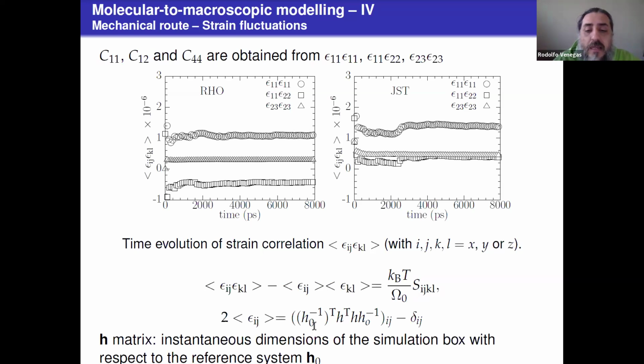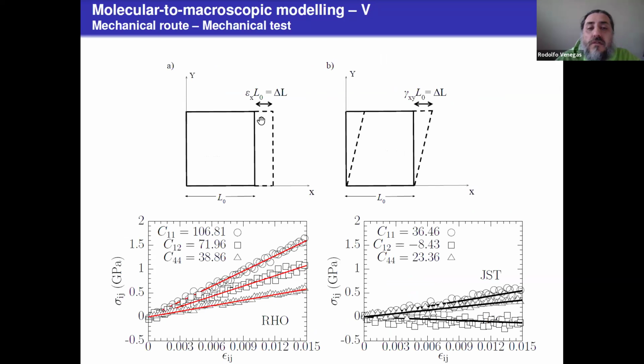In particular, H is the matrix of instantaneous dimensions. When we do the simulation, we work out how this box increases or decreases in size with respect to a reference system, and that allows us to calculate these parameters. So that's the second route. And the third route is, as I mentioned, mimicking the conventional mechanical test. From the stress-strain curves, we can linearly fit in the small strain regime to work out C11, C12, the elastic constants for both types of zeolites.